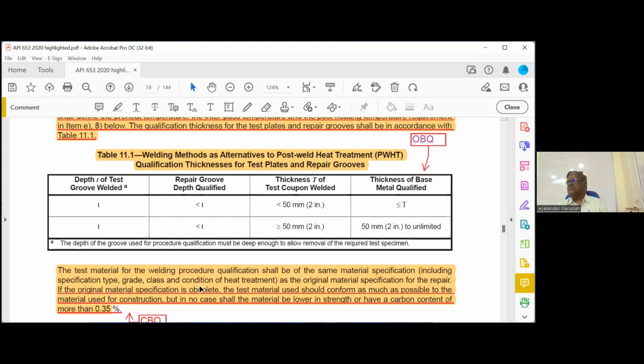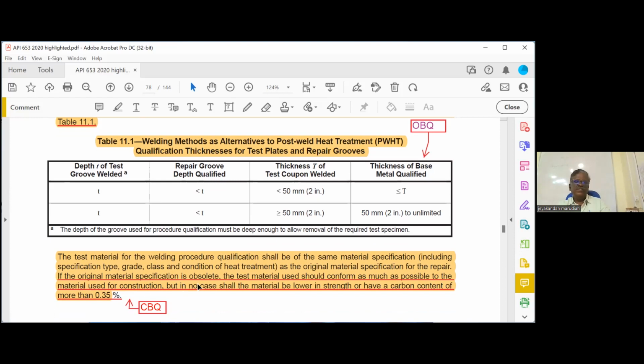Now, another one. Suppose I told you that for making this PQR, you have to take the same tank material. Suppose the tank material is not available. It is an old tank, and that material is not available in the market. So we have to take a compatible material, which is not the same, but the important thing is the carbon percent should not be more than 0.35. Very, very important. If the original material specification is obsolete, the test material should conform as much as possible to the original material, but in no case shall the material be lower in strength or have a carbon content more than 0.35%. That is a closed book question.